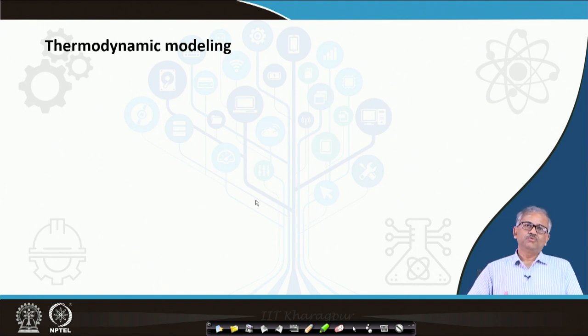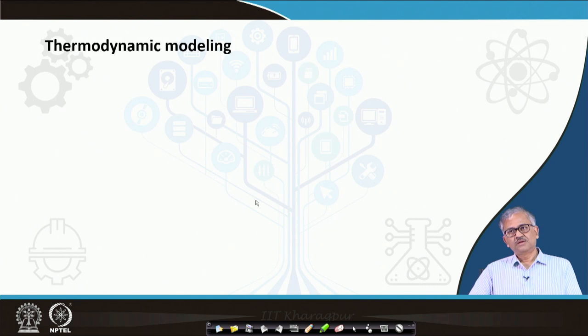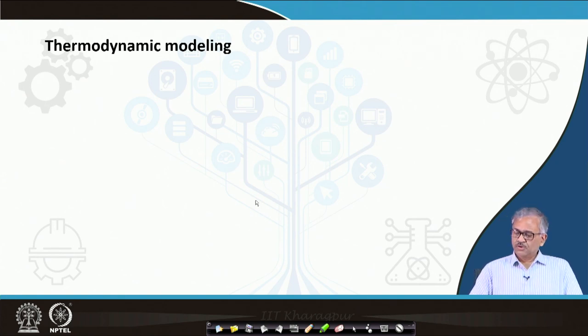If you can do a multi-zone thermodynamic model — that means if we divide the whole calculation domain or reactor into a number of reactors and connect them by input-output flow from one reactor to another reactor — then it moves a little closer to the real situation.